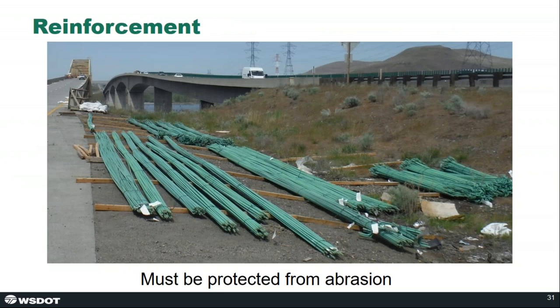A quick point about our epoxy coated reinforcement. It's an effective coating, but it can be weak when it comes to abrasion. So it's very important that this rebar is protected from abrasion in the field if we want it to perform as we expect. So it needs to be bunked off the ground like you see here, and it's important that the iron workers don't drag it over previously tied reinforcement. And it's important that all of the intersections be tied using epoxy coated wire rather than uncoated wire.